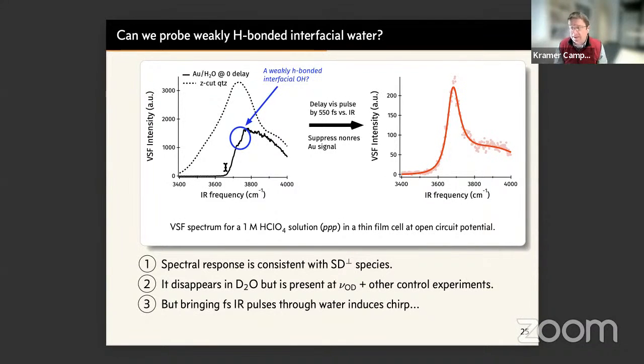If you do spectroscopy, one way to think about this is maybe it's a Fano resonance, right? A narrow spectral feature from an interfacial OH that sits on top of a broad background from the metal. And if you know what a Fano resonance is, a broad background means that its dephasing is very rapid. And so you can imagine now, if I can sample this in time, so slightly delay the infrared pulse with respect to the visible pulse, the metal electron response will have dissipated and only this interfacial molecular response will be left. And this is what's done here on the right. If you delay by about 550 femtoseconds, you end up with this narrow feature.